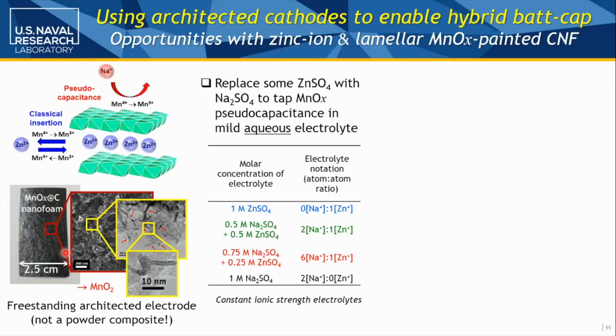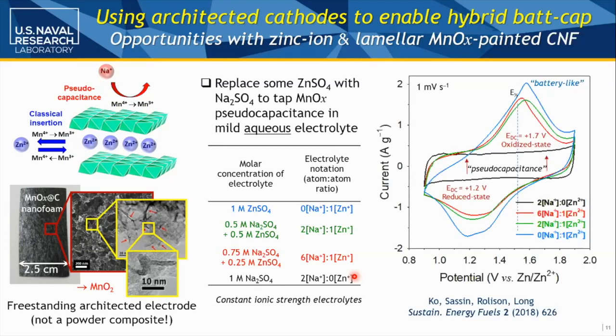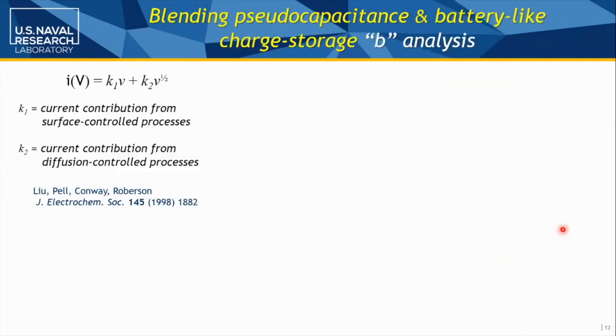And we wanted to play games because we knew this was a highly pseudocapacitive system. So we're going to start with our Carolina blue all zinc sulfate in the electrolyte, or all sodium sulfate. So this should be acting like a battery. This should be acting like a pseudocapacitive type system. And in between, we blend the electrolytes. But we did it so we had the same ionic strength all the way through, so that wasn't a confounding variable as we studied the electrochemistry. And again, here's our pattern recognition, normalized current across the voltage versus zinc, and the Carolina blue battery-like all zinc sulfate, the black sodium sulfate, again our capacitive envelope, and blending the sodium and zinc in the electrolyte gives us something in between. And let's look at that a little more closely.